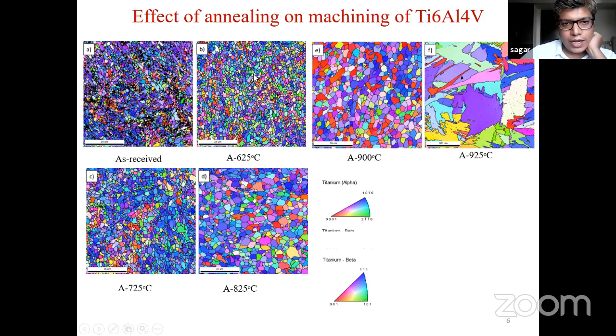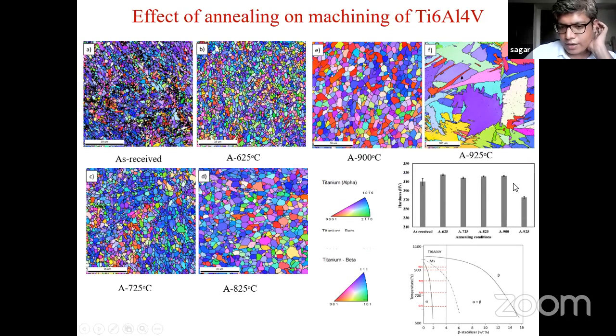Each and every color over here shows a particular orientation at which the atoms have been arranged inside the grains. These are the grains, and the black line shows its boundaries. Here you could see the annealing has affected the grain size and orientation quite a lot. Overall, till annealing at 900 degrees Celsius, there is no domination of a particular orientation. But when you anneal it at 925 degrees Celsius, you could see a completely different structure. That is because you are annealing it near the transition temperature.